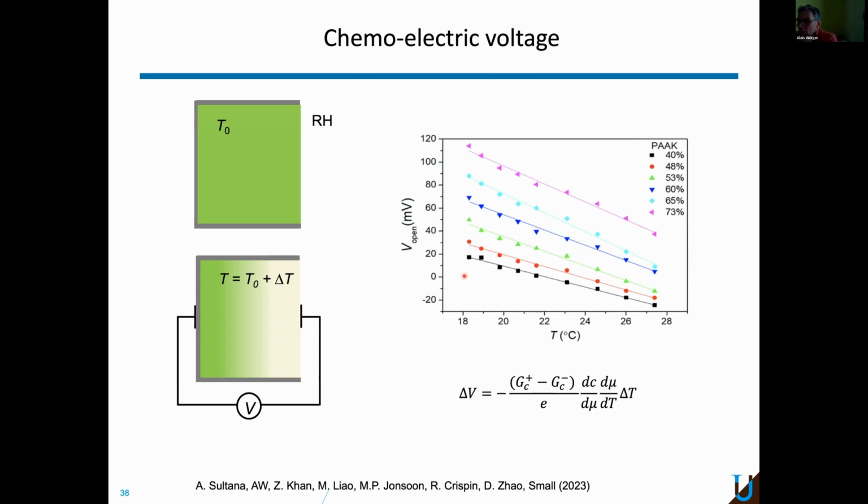I think the large Seebeck coefficient has nothing to do with viscosity. It does not depend on viscosity. It's really the point that, since you have to jump over a barrier, you have to take this whole barrier height energy over the barrier, because a particle takes up its energy on one side and releases it on the other side. This is really the heat of transport, and this is at the origin. As the formula tells you, it's proportional to delta H. For an ion in water, all the energies a particle carries, all the interactions, are just kT. That's why they are much smaller. But I feel that we are moving to the discussion part, so I have to stop.